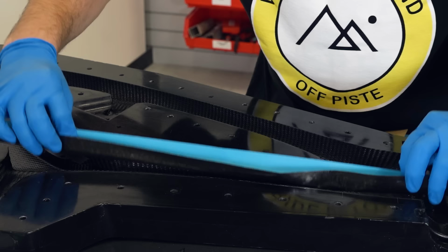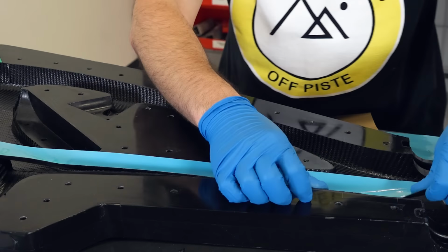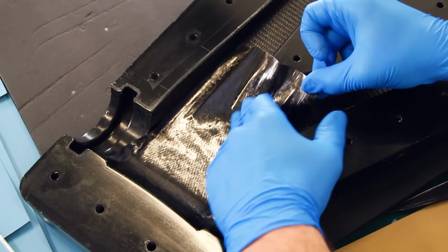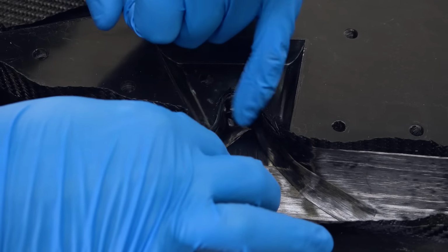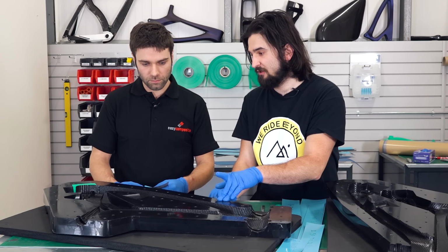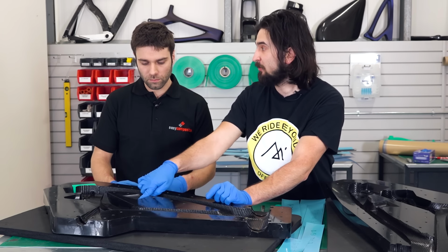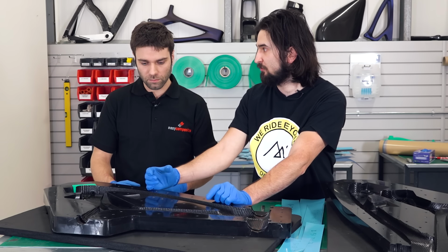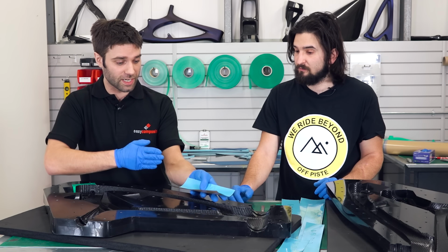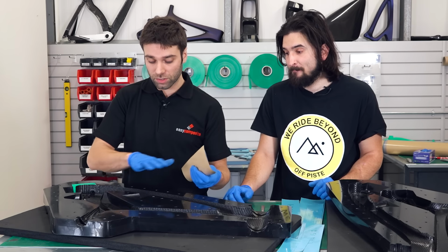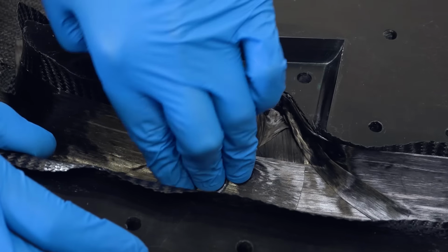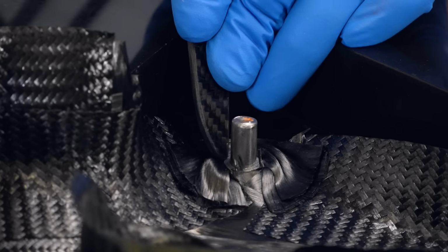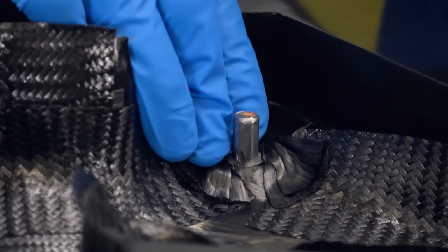So in the case of a bike frame, how do you take most advantage of unidirectional fibres? So the basics are we run along the tubes. So this way we tie head tube to bottom bracket to all the mount points, like where the linkages go and where the shock goes. Another use of the UD is actually around those same points to reinforce and to add extra strength. In the case of a tube, you want the strength down the length of the tube, so we predominantly align the fibres down that way. Yes. And then maybe on mounting lugs, where the loads are going in a different direction, you wrap it round to put the load through in whatever direction it's travelling in. Let's start laminating.